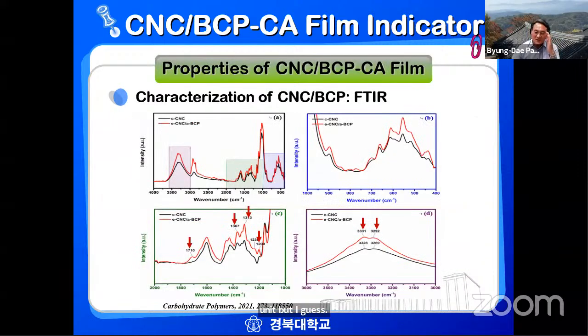And then we checked whether there are any chemical reactions between them. We did this using FTIR, and we have these reactions and spectra. We have carboxylated CNC. This E means esterified CNC with activated BCP. This is a kind of composite material. And then we have new peaks, these kind of peaks. They are responsible for the new reaction between the esterified CNC and the activated bromocresol purple. Also, there are some spectral shifts in the composite materials. These indicate that there is a chemical reaction between them.